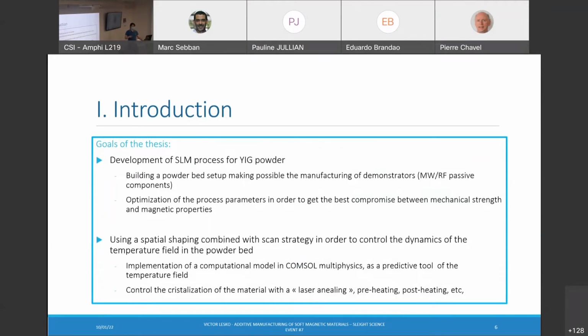There are two main goals in this thesis. The first one is the development of a selective laser melting process for YIG powder, which means finding the good parameters in order to keep the good magnetic properties of YIG, and also keeping good mechanical properties. We want to make demonstrators like circulators and isolators for microwave applications. The other main goal is using spatial shaping of the beam and associating it with a wise scanning strategy in order to control the dynamics of the temperature field in the powder bed.